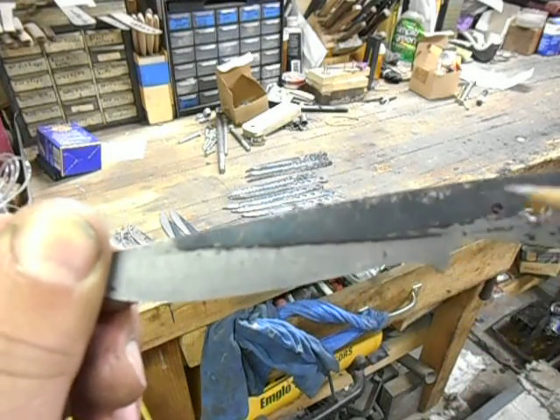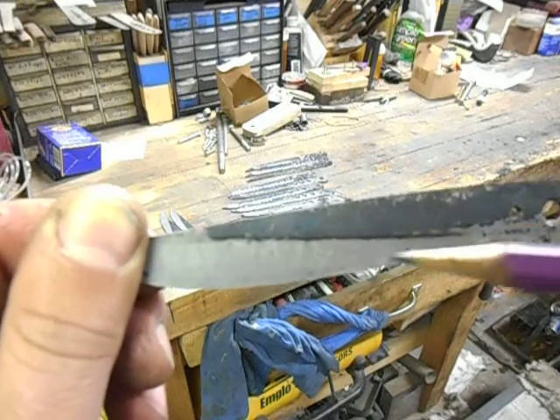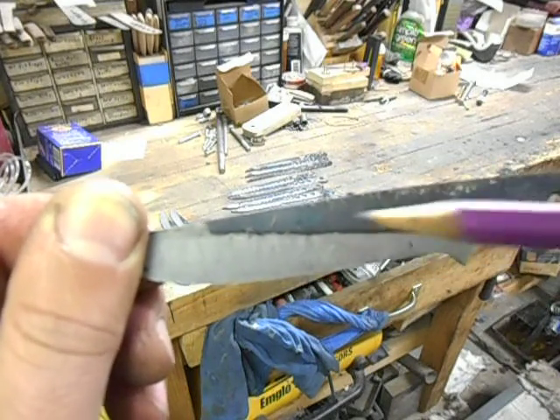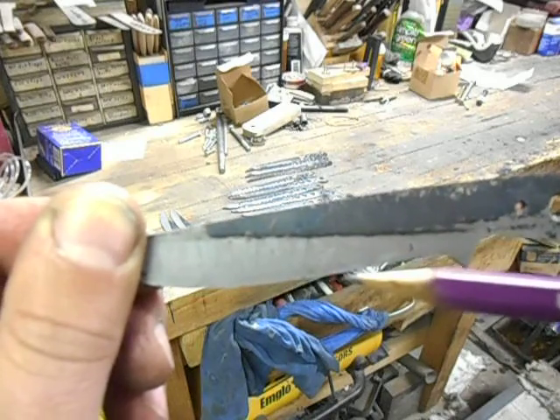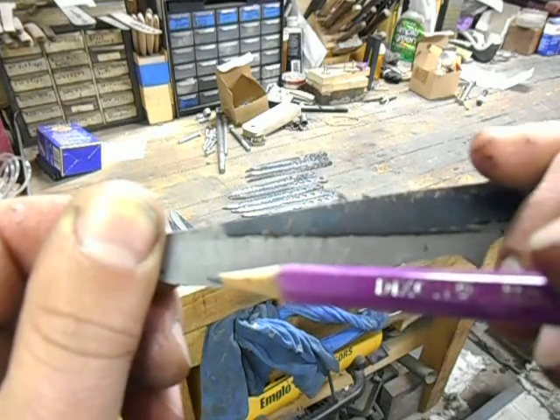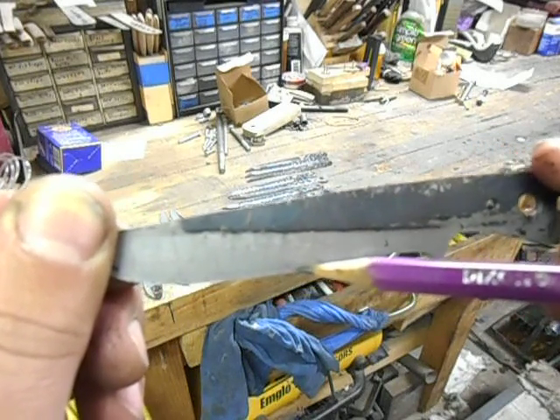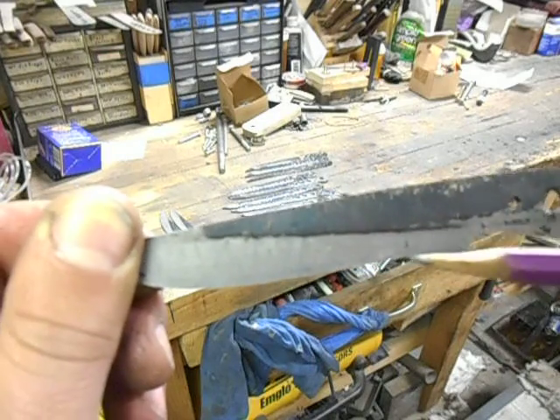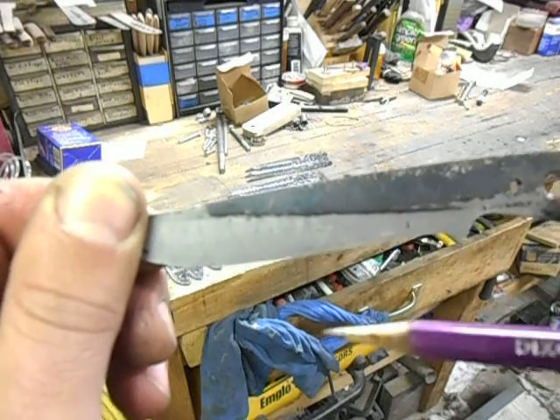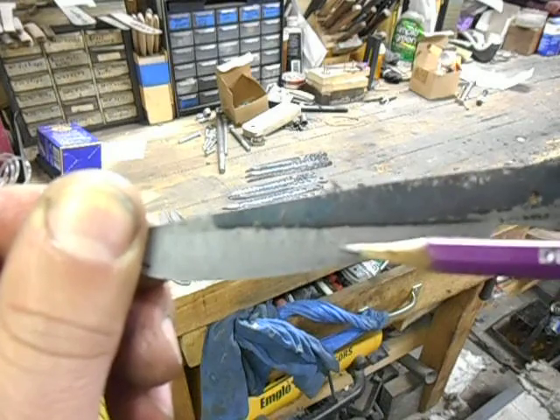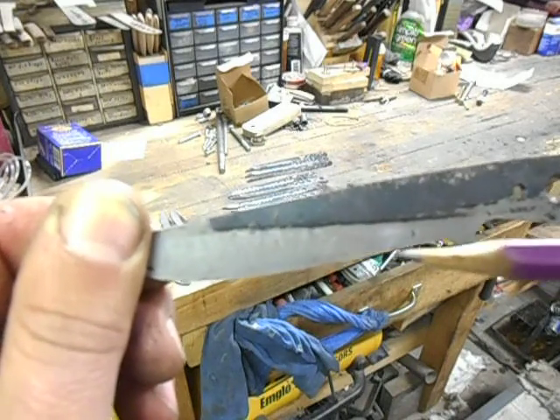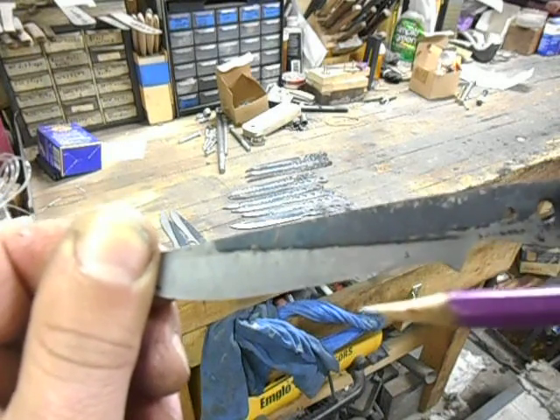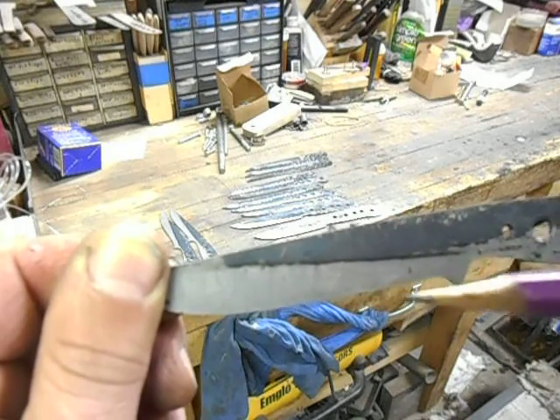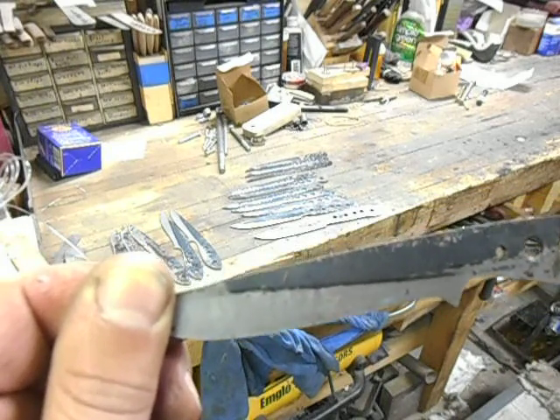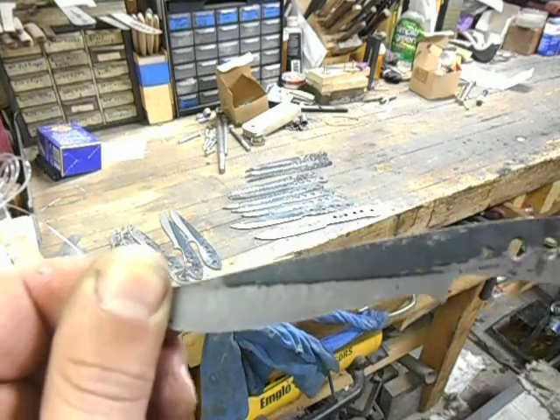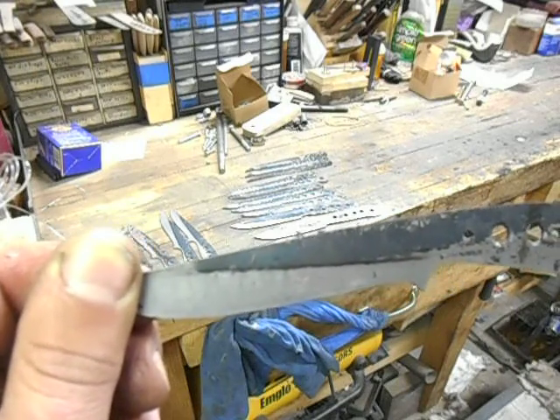So the key to letting you know exactly what happened, that verifies the scale pattern, is that when you sharpened it and you ground off that portion of the edge that was too cold to harden, as soon as you get that gone and you get back into steel that was thick enough to retain the heat from the kiln long enough to make the trip from the kiln to the oil, then all of a sudden, bam, the knife starts cutting like it's supposed to.